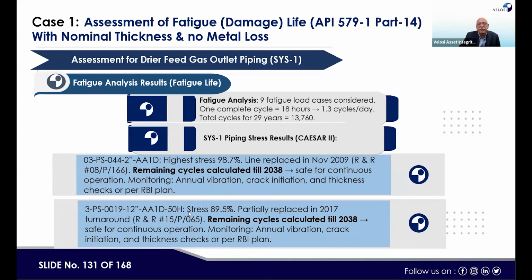For example, for this piping system, stress ratio 89.5%, partially replaced in 2017 turnaround, and remaining cycles calculated till 2038, safe for continued operations. Monitoring annual vibration and crack initiation and thickness checks as per RBI plan. So this was the recommendation. Remember, metal loss wise, these pipes are already safe. Now we have checked as per the number of cycles, and this number of cycles assessment and fatigue analysis are both showing the piping is safe to keep in service till 2038 as per the target of the client.